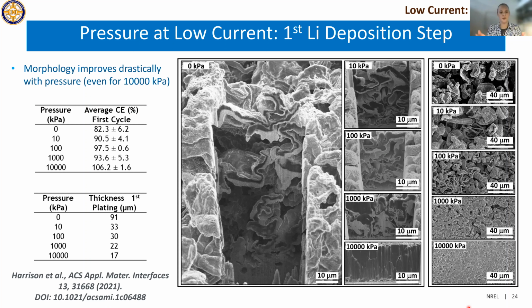And so we had pulled off a separator to do this type of imaging. What you're seeing is, in low current conditions with low pressure, a very open network of lithium. The lithium is the dark contrast here. There's some redeposited material that's very bright here. And there's a very thin layer of SEI that we can see on top of the lithium. It's tens of nanometers thick, and so there's not a lot of contrast here. We could zoom in and get some better images of it, but we couldn't get any elemental analysis, so we didn't spend a lot of time on that.